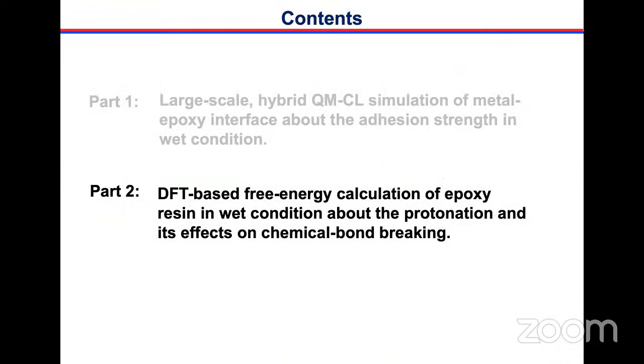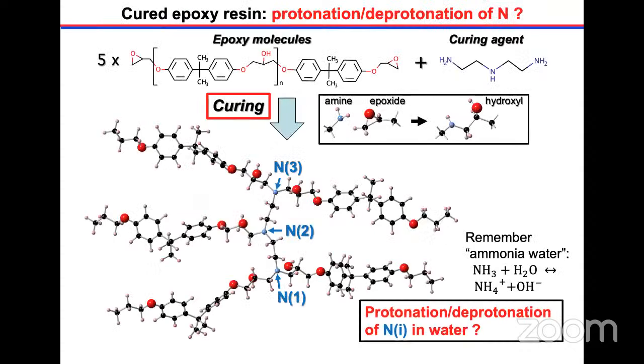Now coming to part 2, free energy calculation and the barrier energy of the chemical reaction. So this is the idea of the curing. We have here five times epoxy molecules, then curing agent, a mixture of this, because the amino and the epoxy group make a reaction like this. Opening of the epoxy group, oxygen and the hydrogen simply changing positions. Then hydroxyl is produced here, and then this is a bridging.